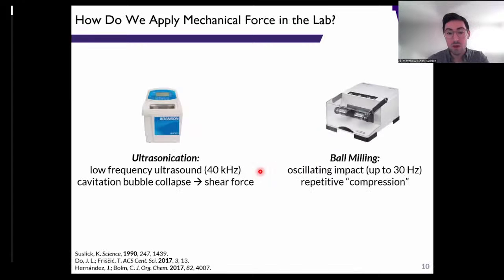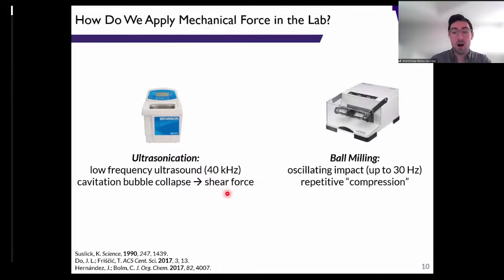So in the lab, we can think about performing these prototypical reactions either in solution using an ultrasonication bath, where low frequency ultrasound produces cavitation bubbles within our solvent media. And the collapse of these bubbles results in tremendous amounts of shear force. This isn't what I'm going to focus on today. This is what some of the field got started on, what we got started on as well. What I really want to focus on today instead is our interest in ball mill grinding. For those less familiar with ball milling, this looks a little bit like a glorified paint shaker.